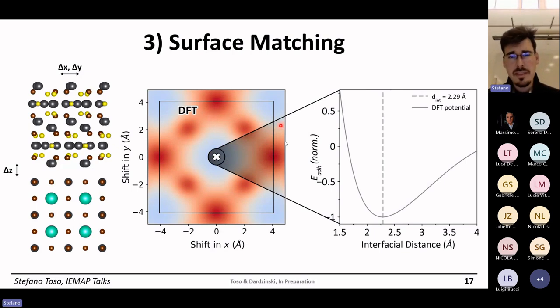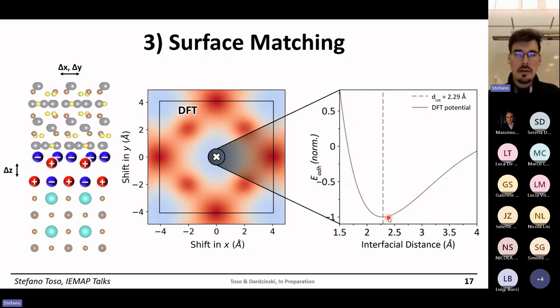Of course, sorry, the energy map is bidimensional, right? So this represents the lateral shift of the two fragments, and this is the bonding distance at the interface where you have a minimum. So here what we did was that we implemented a Coulomb potential. It's a classical electrostatic potential, leveraging the fact that most semiconductors that we work on in colloidal systems, and it's important to remind, are actually ionic or partially ionic compounds like cadmium selenide, cesium lead bromide. They have a strong ionic component to the bonds, so they are acceptably approximated by an electrostatic potential.